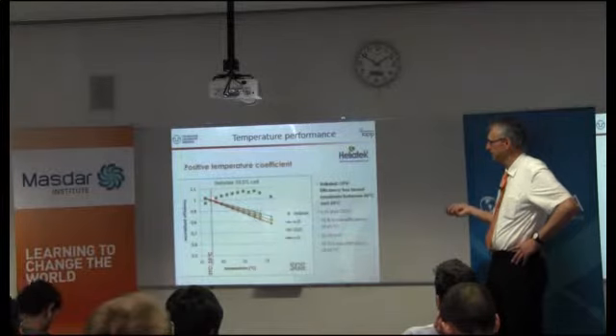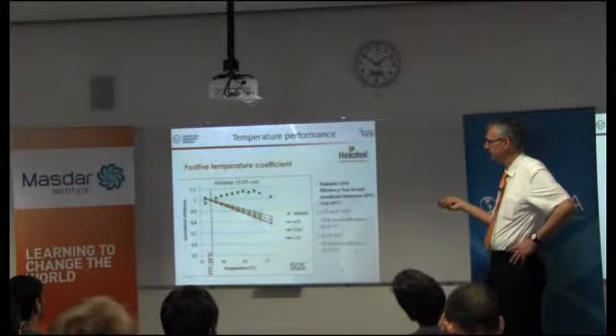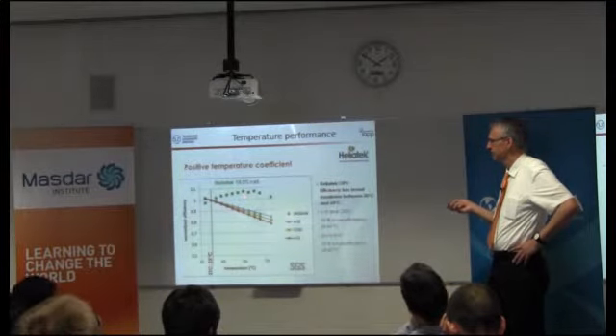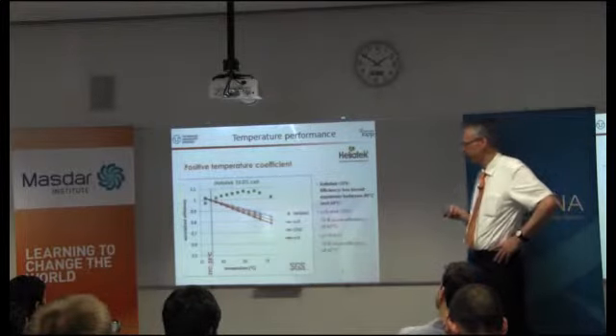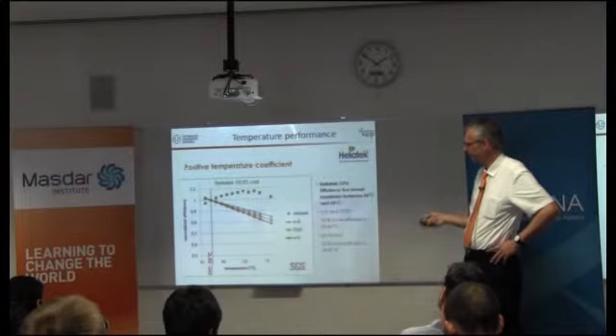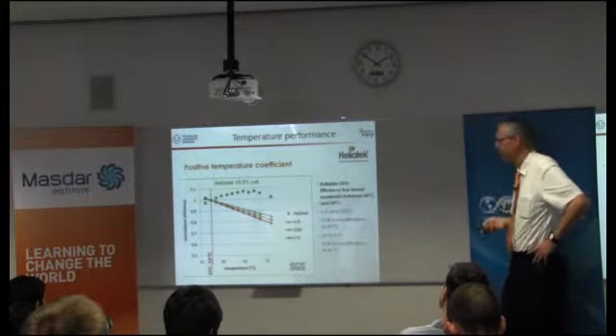This is the standard measurement condition, which is put at 1 for the different technologies. Amorphous silicon, CIGS, and crystalline silicon all go down, whereas the organics is actually at the point where, in a hot country in summer, its maximum is at 55, 60 degrees. Organics gets better by 7-8%, whereas all the other technologies get worse by 10 to 15%. So this is already a huge effect.